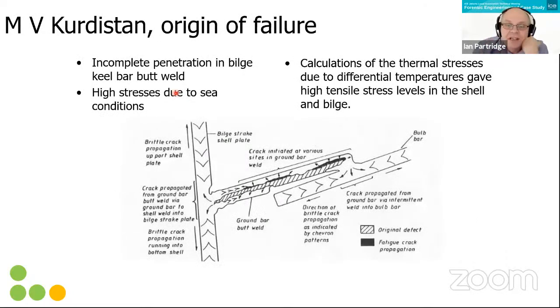This is what it looked like at the bilge keel. The original defect, the original repair with lack of fusion, is that hatched area, and it fatigued this much, so it hadn't fatigued significant amounts. There was high stress at the time due to the sea conditions, 6 meter waves. Also, you had 140 degrees F here and 0 degrees here, so a differential temperature causing stress. Once it reached a critical size, it just zipped across the material. The material acted brittly. If you look at the fracture faces, chevrons can be seen, and these chevrons point back to the area of failure.